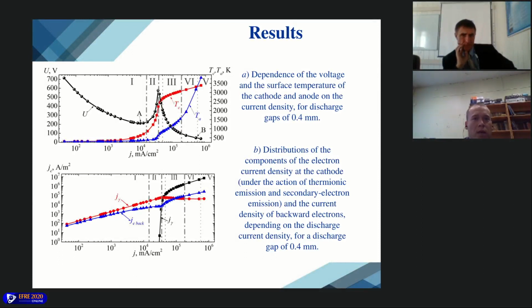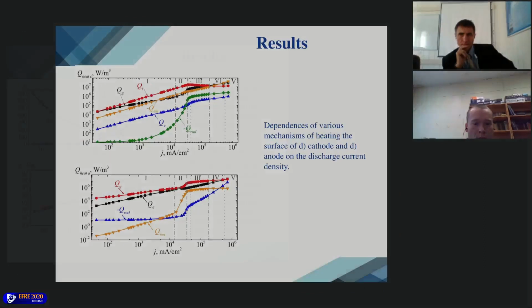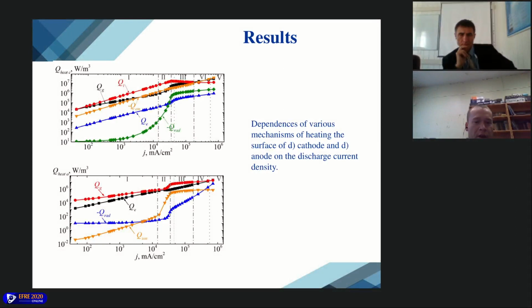On this slide, we can see dependencies of the voltage and surface temperature of the cathode and the anode on the current density for discharge gaps of 0.4 millimeters. And here we can see the distribution of the components of electron current density at the cathode: thermionic emission, secondary electron emission, and backward electrons. And on this slide, we can see dependencies of these mechanisms of heating the surface of the cathode and the anode on the discharge current density.